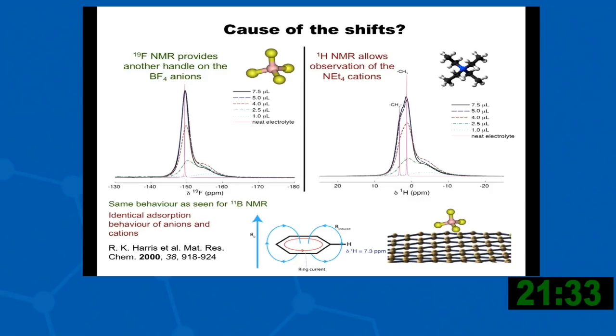It turns out the shifts are not due to the chemical environment, they're due to a susceptibility effect. And they come from the fact that these ions are sitting on top of these large graphene sheets that are highly aromatic. And for those of you who remember your organic chemistry, you'll remember that benzenes have ring current effects that dramatically affect the proton NMR of a benzene molecule. And in the same way, if you're a molecule that sits on top of a benzene ring or a graphene sheet, you get a shift due to this effect.